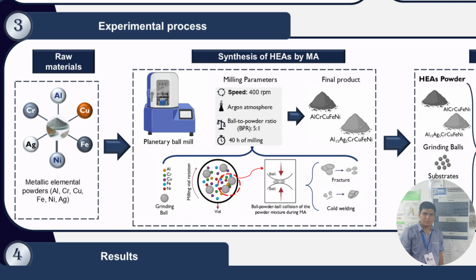The powders were loaded into a planetary ball mill running at 400 revolutions per minute under a protective argon atmosphere to prevent oxidation. We utilized a strict 5-to-1 ball-to-powder weight ratio. During this 40-hour milling process, the particles underwent continuous cycles of cold welding, fracturing, and rewelding due to the high energy impact between the balls and the powder, resulting in a refined nanostructured product.